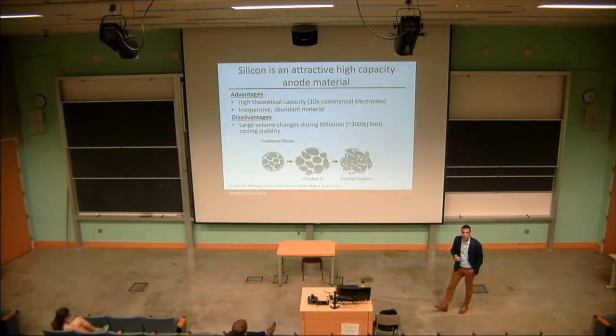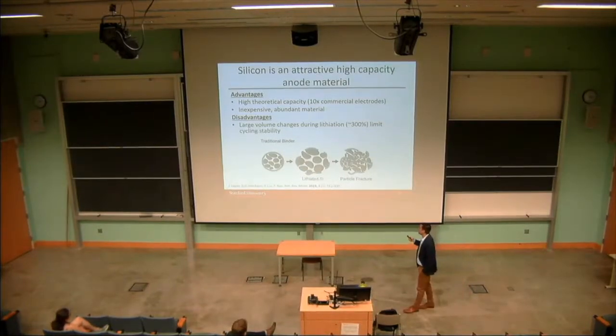Because of the low potentials of the silicon electrode, the electrolyte will react at those surfaces, and that consumes lithium and consumes silicon and increases the impedance of your cell, lowering the performance. And then additionally, you have particles that become electronically and ionically isolated. And what that does is you lose their capacity. They either stay charged or stay discharged, and so your capacity fades from that mechanism as well. So any attempts to stabilize silicon really need to address this particle fracture and particle isolation issue.